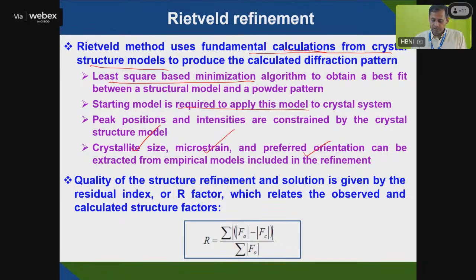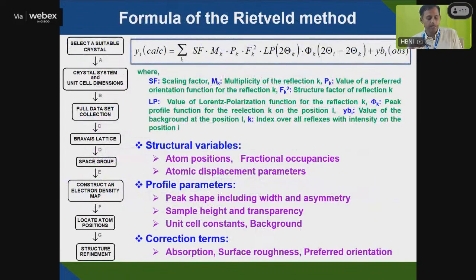analysis. And whether your analysis is good or not, you can identify by a quality-of-refinement factor, the residual index or R factor, that is |F0 minus FC| divided by F0, which compares the calculated to the originally obtained parameter. And if you see the whole Rietveld formula, here is the structure factor, this is the multiplicity factor, this is the polarization factor. Then you have the observed Y. So all these parameters: SF is the scaling factor, then multiplicity, then the preferred orientation factor PK, F squared is the structure factor, LP is the Lorentz-polarization factor, phi is the peak profile function, and theta, all those parameters are taken.